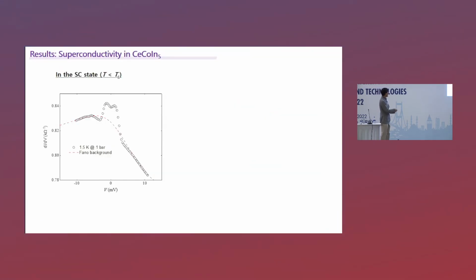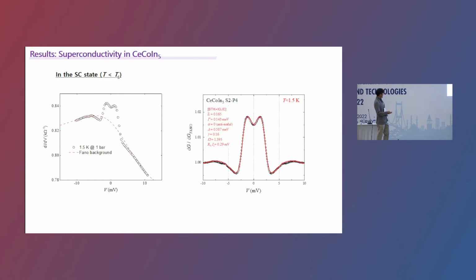Okay, so this is differential conductance as a function of bias voltage of CeCoIn5 at ambient pressure in the superconducting state. What you see is that there is a broad background from the Fano resonance and then an enhancement at zero bias due to Andreev reflection. In order to amplify this Andreev reflection feature, we divide this conductance by the normal state. Then what you see is a nice two-peak structure that you expect from the superconducting Andreev reflection. And here, the red line is a fit using the modified BTK model with a gap size of about 0.587 millielectron volts.